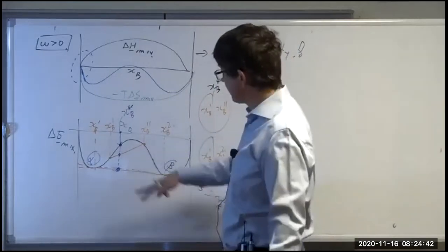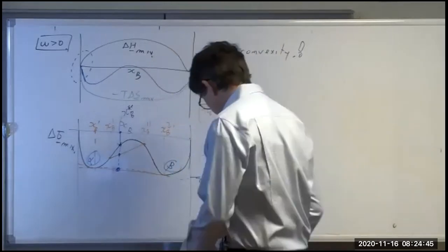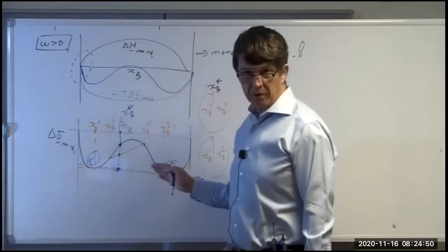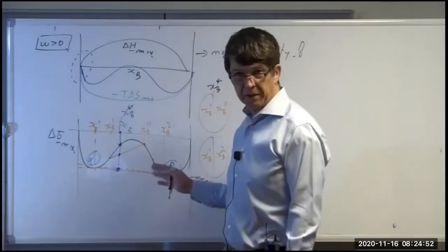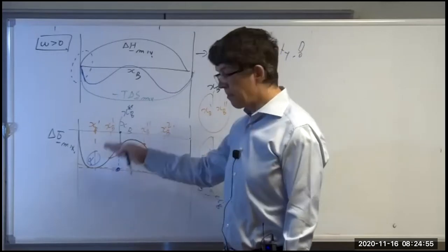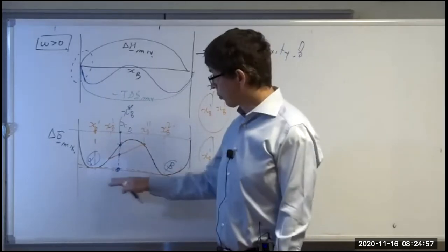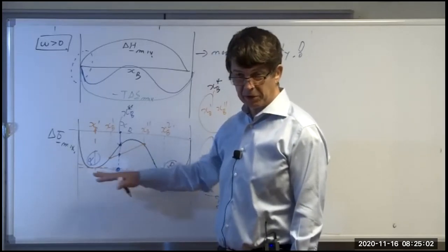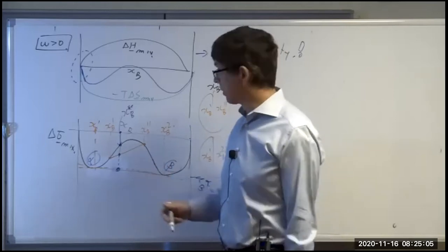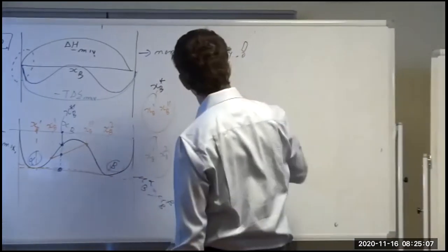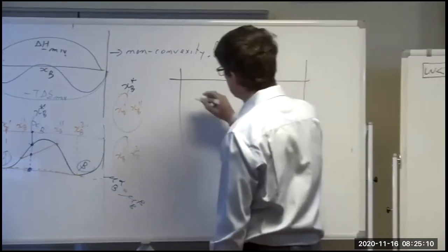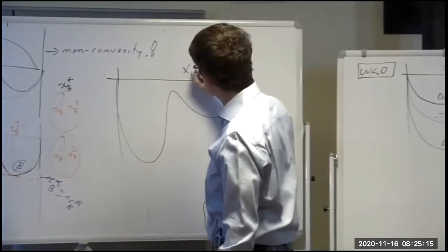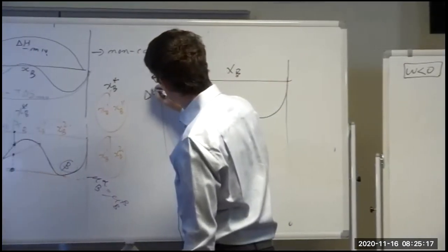I want to say something about this construction because I like explaining this by the regular solution model, but there is sort of one failure of the regular solution model that's really annoying. Because it's symmetric, the common tangent points are in the minimum, right? Because the common tangent has to be horizontal, but in reality, I've never seen in my life a symmetric free energy curve of a real system. So in reality, it looks something like this, right? So very asymmetric, delta G of mixing.